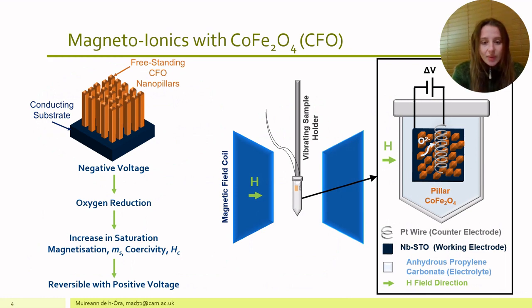The next element of my work was magnetoionics using cobalt ferrite. So instead of a cobalt ferrite matrix, in this situation I was using cobalt ferrite nanopillars fabricated in the same way. These pillars are single crystalline, and their high surface interface with the liquid electrolyte when doing magnetoionic experiments allows for large ionic migration. So when I apply a negative voltage, the oxygen ions migrate into the liquid electrolyte, and this causes an increase in saturation magnetization and coercivity, and it's all reversible with a positive voltage.